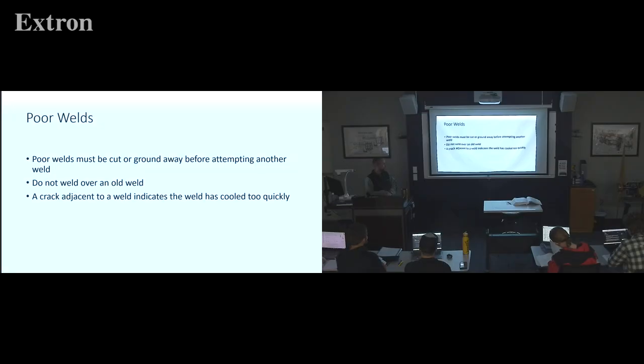Okay, this is not your tractor, okay? A crack adjacent to a weld indicates that the weld has cooled too quickly. So if it cracks just on the other side of it, potentially it got too cool. Okay? Please don't go pour water right on top of your weld after you've welded it so you can touch it. Why? What's the problem with that? It's going to cool it too quickly, which is going to only cool the surface and crack the surface. Yeah. Good.